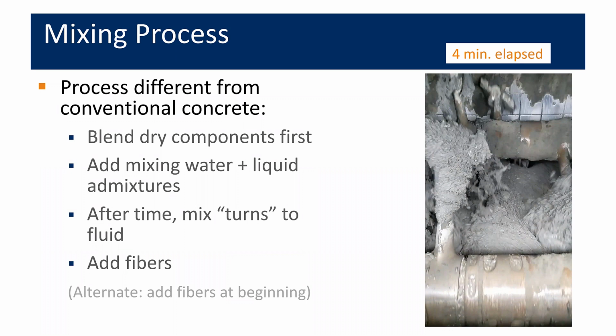And typically, it's at this time period that fibers are added to the material. There have been attempts to add fibers earlier in the process, as a means to speed up the process, and that can be successful as well. But again, the more typical process is to wait until you get that fluid consistency before adding in the fibers.